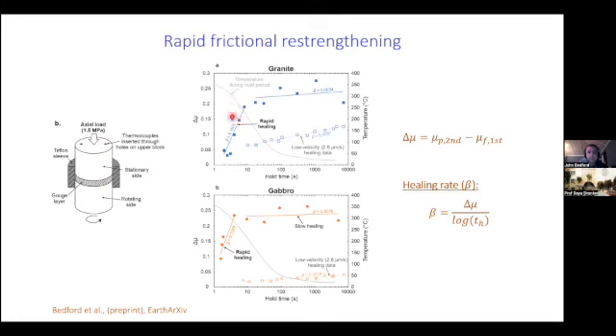The sample cools during the hold period, but it takes several tens of minutes actually for the temperature to reach the sort of ambient temperature in the laboratory. And if you look, this rapid healing occurs while the temperature is still above sort of 250 degrees Celsius. The rapid healing is occurring while the material is still hot from shear heating after high velocity slip.